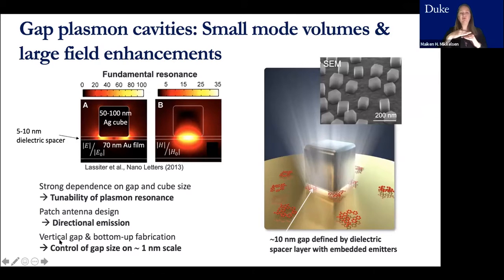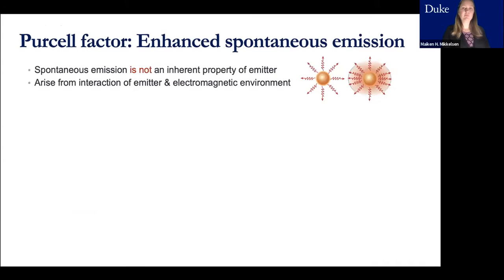And we're utilizing this vertical gap and bottom-up fabrication technique, so we can control the gap size on a single nanometer scale. Often what we do is use layer-by-layer deposition of positive and negative polymer, which allows us to build this up with this critical, almost atomic-scale precision. So the first thing we wanted to explore